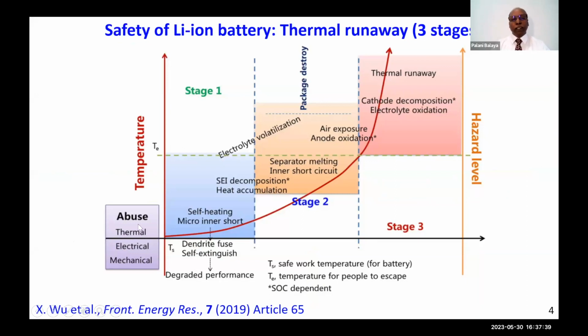But occasionally, these batteries may go through a certain level of abuse. It could be thermal abuse or electrical abuse or mechanical abuse, knowingly or unknowingly. That might cause a so-called micro inner short, leading to self-heating, local heating. And if we ignore this abuse over a long period of time, this leads to subsequent effects. For example, SEI on the anode side, which is the graphite in most of the examples I've shown. SEI, solid electrolyte interface, is the graphite and electrolyte reaction product, and there is a soft polymer layer that gets decomposed, and again heat starts accumulating.